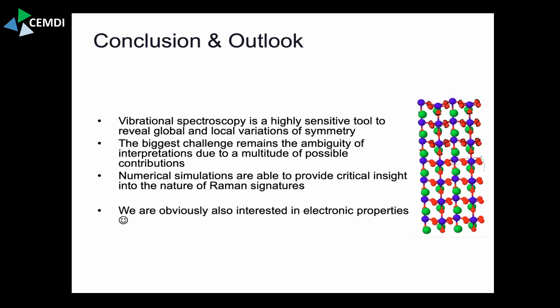Sure. So one of my questions is very general. In the catalysis field, we struggle with selectivity of materials. I am just wondering if these phonon modes can be used to determine selectivity of a material. For example, in CO2 capture, if you have CO2, nitrogen, and so many gases in the atmosphere, one of the biggest challenges is how can we capture just CO2 with this material, and how the vibrational modes of CO2 can determine the activity of the catalyst? Or is it too far?